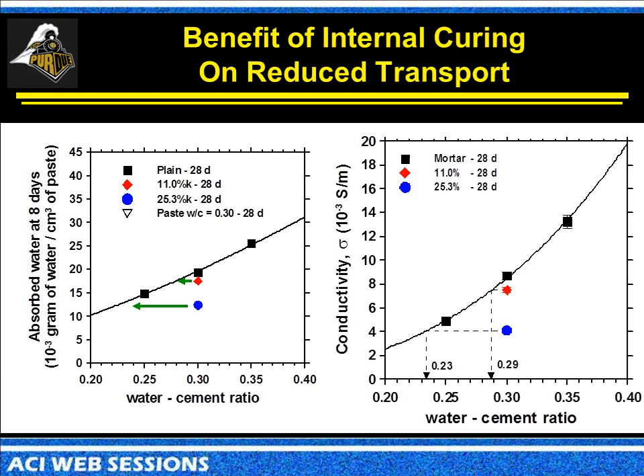All right, so as we alter the water to cement ratio, we know the system is going to get tighter. We know it's going to be harder for fluid transport in the system. But this blue dot is the chemically required amount of internal curing water in the system. So even though it's mixed with a 0.3 water to cement ratio, it behaves like a 0.23 water to cement ratio in terms of allowing additional hydration, densifies the microstructure, fills in the interfacial transition zone. So there's a big benefit of this in terms of internal curing as well.